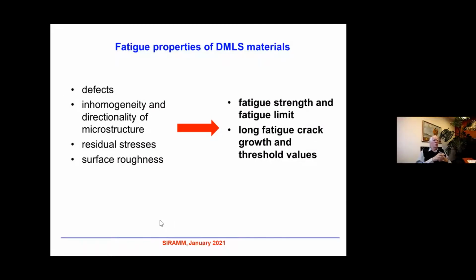So let me now conclude that fatigue properties of direct metal laser sintered materials strongly depend on defects and their distribution, on homogeneity or inhomogeneity and directionality of microstructure, on residual stresses and microstresses, and naturally on surface roughness. It means that all these parameters strongly influence fatigue strength and fatigue limit, and also long fatigue crack growth and threshold values. I would like in the next part to show you some concrete results which we obtained on materials produced by direct metal laser sintering.